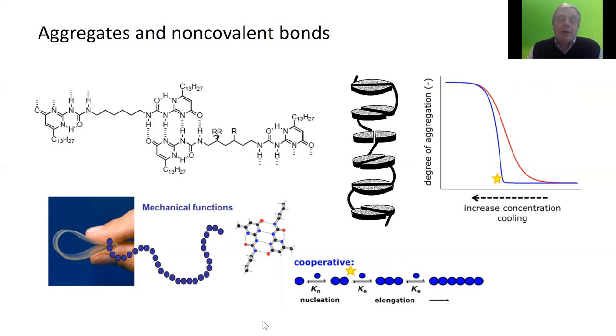But there's a trick about these type of materials which goes a step further. And this unit is a flat unit and it can stack. And when it stacks, there's pi-pi interaction, there are certain interactions in there. And what you have then is that actually they form something like a cluster. In this case, the cluster is this column type structure in there. But that means if they stack together, you have more in one stack than just two linking units in there. And that improves the strength of the stack.